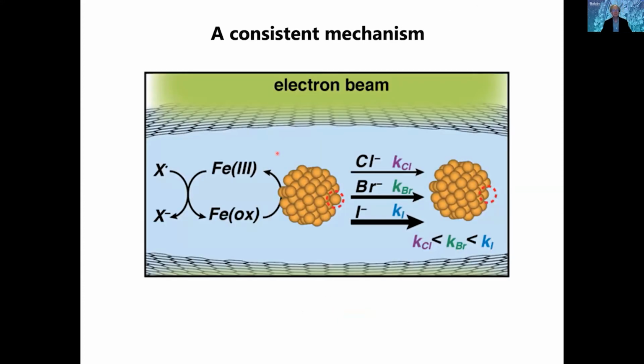So in the end, what we believe is the correct mechanism is to create a highly oxidized iron species, and that oxidized iron species is what is then oxidatively etching the gold. As for the role of the halide, all of our available evidence suggests that these halides are forming complexes with the gold. You form gold chloride, gold bromide, gold iodide species, and the iodide species has a much stronger binding energy with the gold plus ion in solution compared to the chloride or the bromide. So essentially, the iodide is almost pulling the gold atoms out because it binds to them so strongly. We believe that's the mechanism of the oxidative etching in this case.